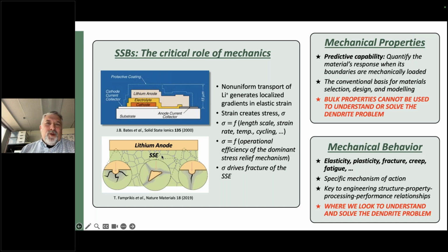Yeah. And so during charging, the lithium ions are obviously traveling through the separator. And in a perfect world, we just plate one atomic layer at a time of lithium back to the anode, right? But in reality, what we end up getting is this preferential plating that occurs within these morphological defects here at the interface between the anode and the solid electrolyte separator, right?